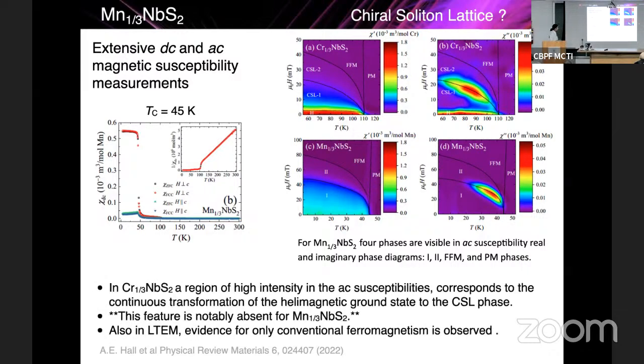So what we've concluded just from these experiments, as well as from the Lorentz transmission electron microscopy, is that the manganese third niobium sulfide ground state just exhibits ferromagnetism, not helimagnetism. And although it's very, very similar to the chromium third niobium sulfide, the ground states are very different, okay?